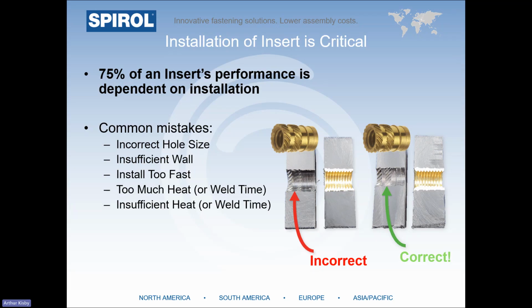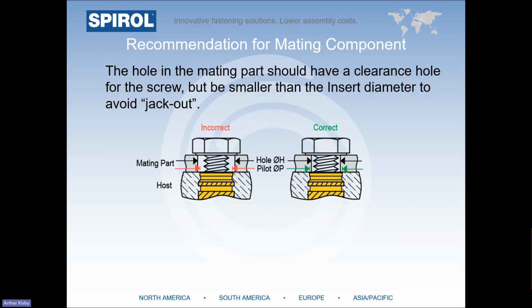Although some common errors that lead to poor installation are listed to the left, the example shown here appears to be the result of a hole size that was a bit too large. Not enough plastic was flowing into all the retention features in the knurls. It's not just the interface between the insert and the plastic host component that is critical to performance.